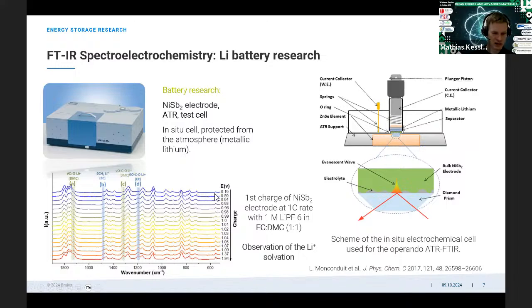And what we see is if we increase the potential, then we see that additional bands occur. And these bands are related to lithium, which is dissolved and then solvated by parts of the electrolyte, which is either ethylene carbonate or dimethyl carbonate. And this solvation of the lithium ions can be then observed directly operando, so in the process of the reaction. So for such investigations, ATR FTIR spectroscopy is a very useful tool. And we use for such experiments our benchtop FTIR spectrometer.